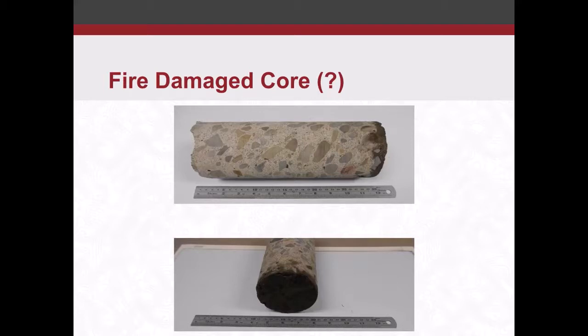So we could compare those near surface aggregates and those deeper aggregates, say at 2-3 inches. It's the same aggregate, the same type of stone. We could see the difference under infrared light. Those near surface aggregates were fractured, and the deeper ones didn't show those same fractures. So yeah, there can be some value in petrographic analysis, and sometimes we might do both. We quite often piggyback multiple test methods together to give us more information.